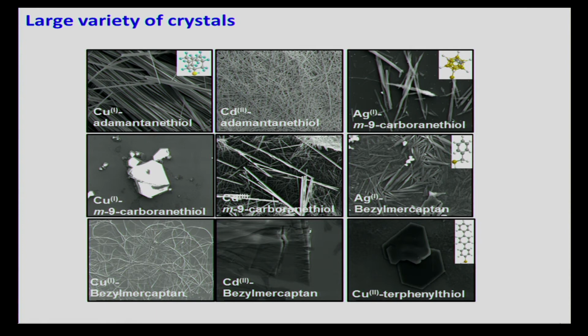And we can do it for a lot of different species. We can do copper, we can do silver, we can do cadmium, we can do mercury, we can do lead. And on the diamondoid side, we can bond them to all kinds of different diamondoids with different sizes and shapes, and they end up having different morphology in the crystal that they grow, but they all end up having a very highly crystalline material structure.